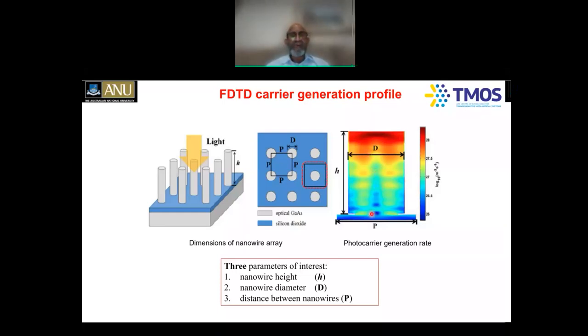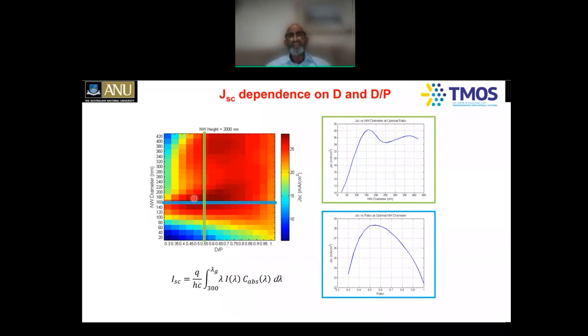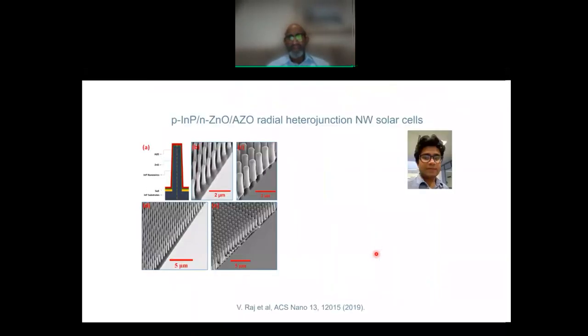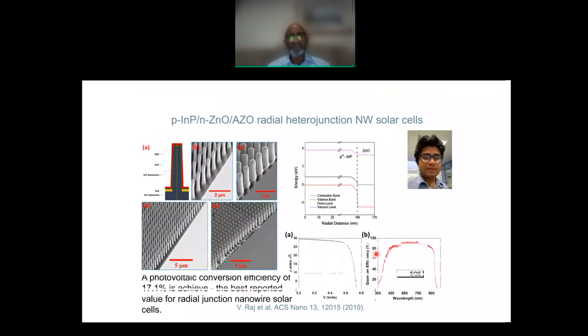And then again, we've looked at the diameter, and you can see the red means high current, and you can see that the diameter should be around 150 to 160 nanometers. The pitch ratio should be around 0.5 or 0.6. And again, these simulations are really playing an important role. This is the work of my young colleague, now at Glasgow University, who did his PhD with us at the ANU, Dr. Vidur Raj.